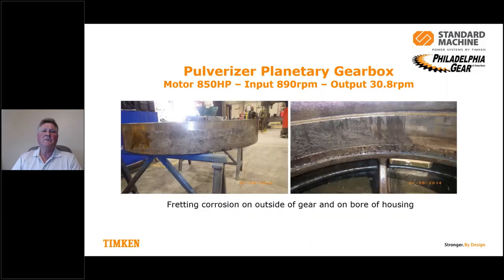Once we removed the ring out of the housing, you could see the fret corrosion on the gear and the bore of the housing, a tremendous amount of sliding and rocking action. And you can actually see where the gap was on the housing, where it had moved up. And the etching and the corrosion was mostly done after the gear had moved up, the ring gear had moved up in the housing.